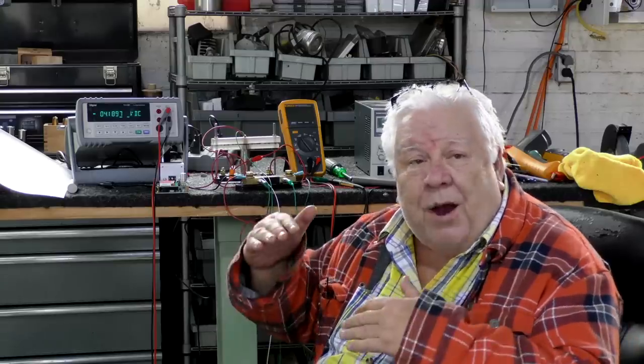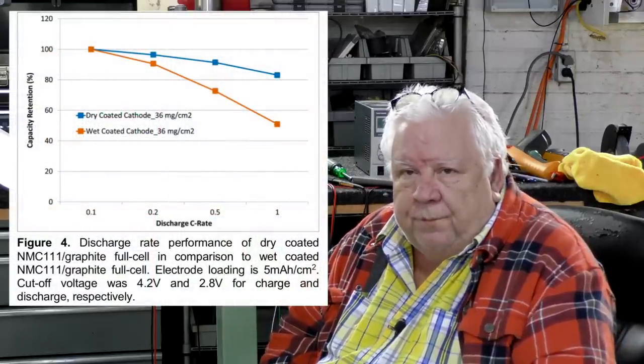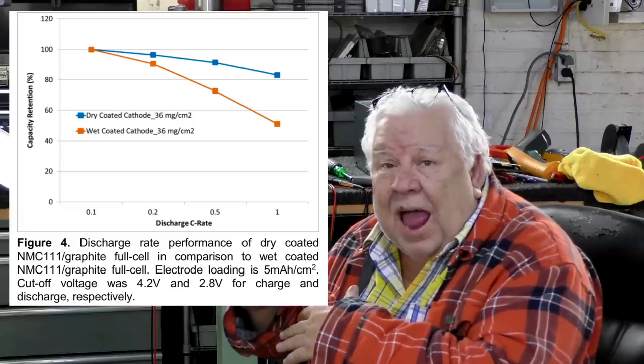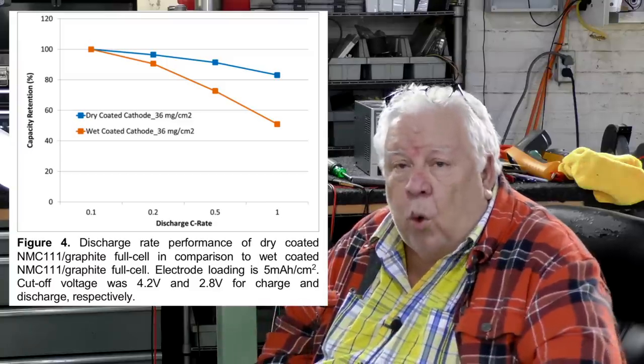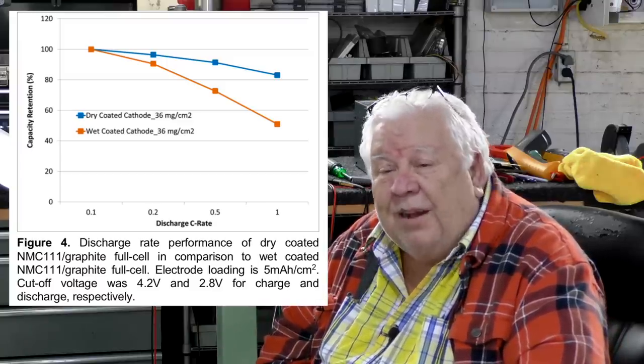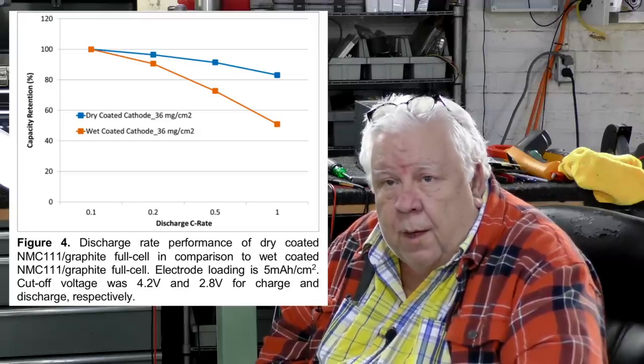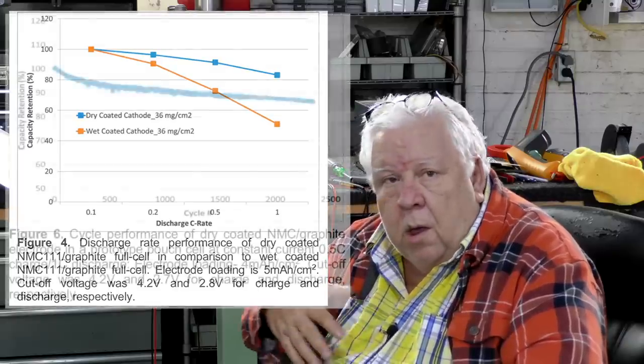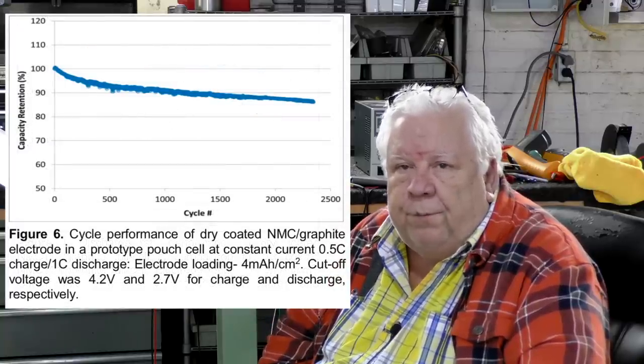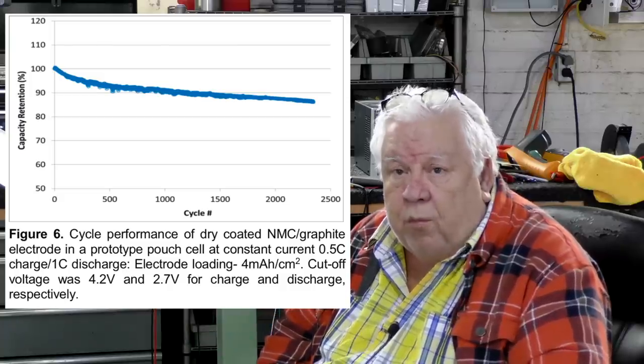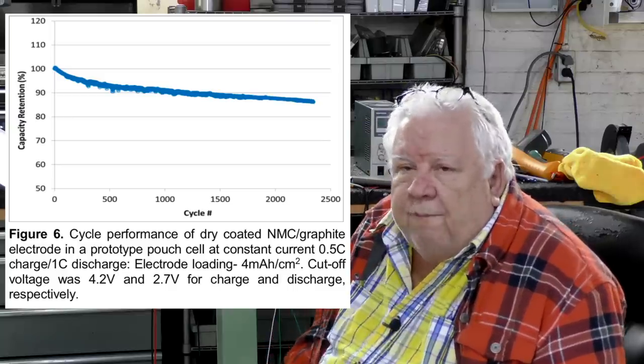The story is that that disparity between the capacity of the cell at different discharge rates was flattened by half. Now, there's still a disparity between 1C discharge and 0.1C, but it's half of the disparity that it was. And the other thing was the cycle life of the cells went bananas, over 2,000 cycles. That's like LiFePO4 cells, but for the NCMs and NCAs. So there were two very significant advantages in the performance of the cell that they were just trying to make sure they could do as well as using this new manufacturing process, which is less costly by a lot.